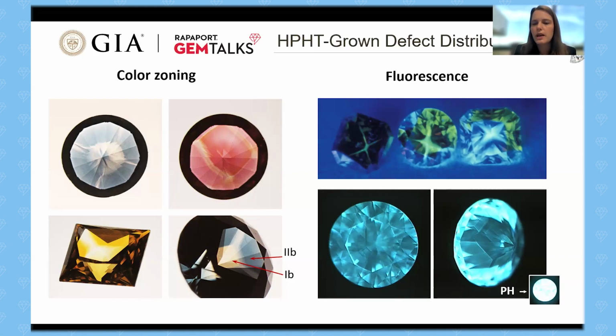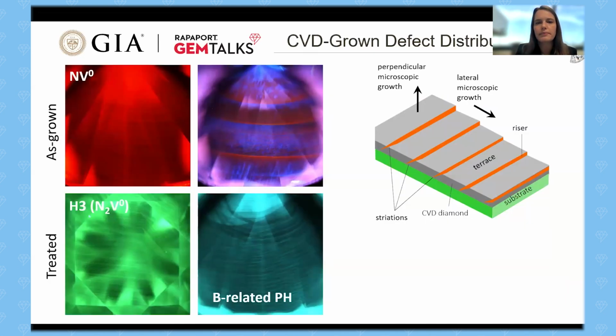and that's going to create a pattern that can be seen even in high purity type 2 HPHT grown stones. In particular, these UV light sources are also able to induce phosphorescence, where the sample continues to glow even after you remove the UV. Now, phosphorescence is something that is extremely rare in natural diamonds, so being able to observe this can be a good warning sign that the diamond needs to be looked at more carefully.